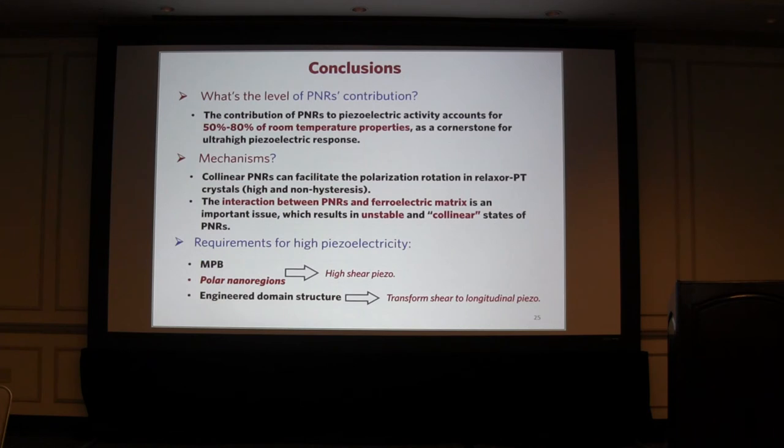So what's the requirement for high piezoelectricity here? First is the morphotropic phase boundary, and then polar nano regions. Because of these two factors, we can have a very high shear piezoelectric coefficient for a single domain. And we do need to engineer the domain structure. By this domain structure, we can transform the shear piezoelectric response to the longitudinal piezoelectric response.